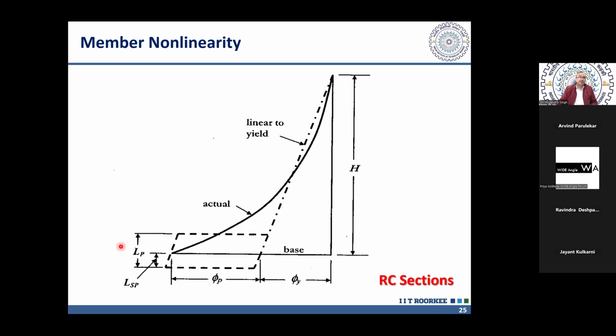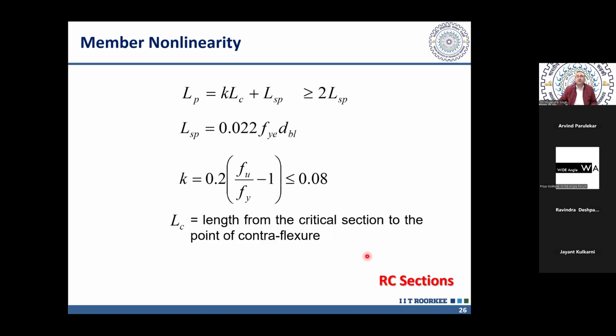So this Lp, the plastic hinge length, is obtained empirically from experiment by adjusting this length in such a way that the displacement which we are calculating from the moment curvature diagram at the top matches what we are getting from the experiment. So this length is a smaller length here. Sometimes people get confused that this is the length in which steel is yielding. But plastic hinge length is not the length of yielding. Yielding occurs in a much longer length. Plastic hinge length is just a notional length which is calculated in such a way that if I consider the plastic deformation to be lumped in this length only, then I will get the same displacement as obtained from experiment.